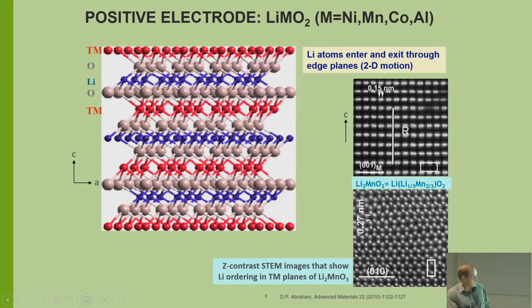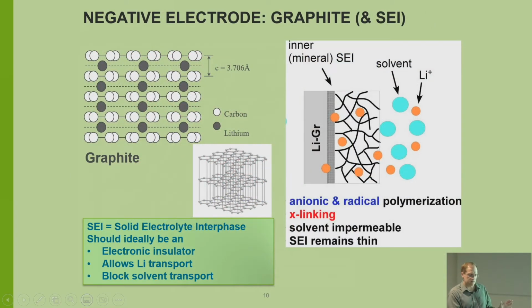Now, if you look at the negative electrode, graphite has basically honeycombs all together, and then they're stacked on top of each other. So here's your lithium atom, and that sneaks in, and its electron comes with it, and that's sitting in between these two rings. You picture a ring of carbons above it and a ring of carbons below it. And like I said before, when lithiated graphite is fully charged with lithium, it wants to react with almost everything, including the electrolyte. The electrolyte reacts at about 0.8 volts above lithium potential.